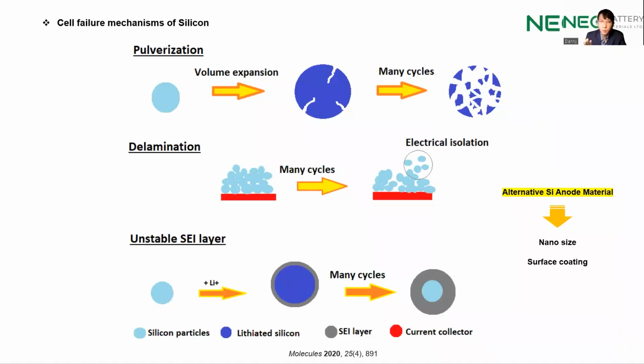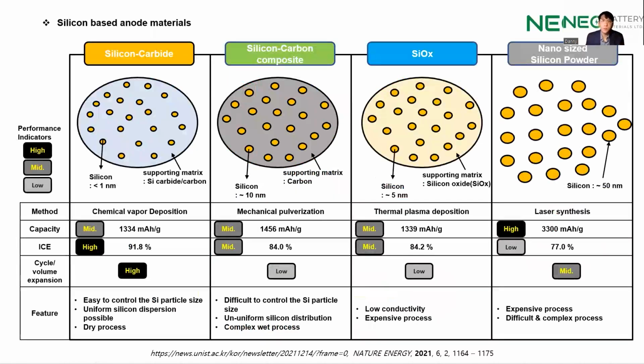So two solutions have been proposed as one of the alternative efforts for using silicon-based anode materials. So one would be to decrease the size of the silicon into the nanoscale, or to modify the silicon surface itself. So let us compare some silicon-based anode materials that have been currently developed or are under development. The categories can be largely divided into four groups: silicon carbides, silicon carbon composites, silicon oxides, and nano-sized silicon powder. So except for the nano-sized silicon powder, the current options utilize a supporting matrix, you can see here on the circle, to form silicon composites.